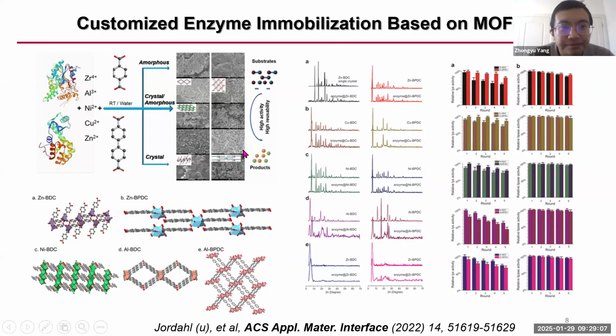And some crystals, like zinc BDC, right? Those are zinc BPDC. Those are almost near single crystals, very, very high crystallinity. And some we have to fit the powder XRD data with a multi-phase. And some we cannot fit anything, like the copper BDC, the copper BPDC is completely not crystal. But still, it's a solid, it feels like a gel.